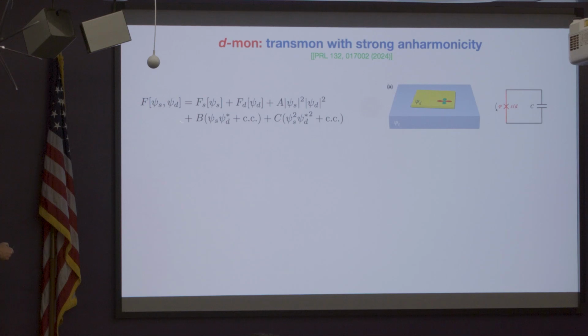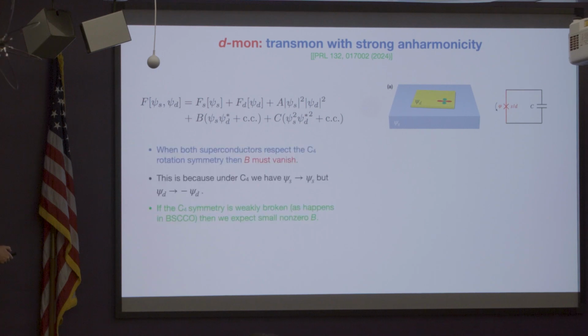Similar to our analysis with D-wave, I have these terms. However, if both of these materials respect C4 rotation symmetry, as cuprates do, and if we put in an S-wave superconductor that is tetragonal, then this would be the case. We can conclude that, again, this B term has to vanish. And this is because under C4, the S-wave order parameter is invariant under C4 rotation, whereas the D-wave order parameter goes to minus itself. So this term is just not an invariant, right?